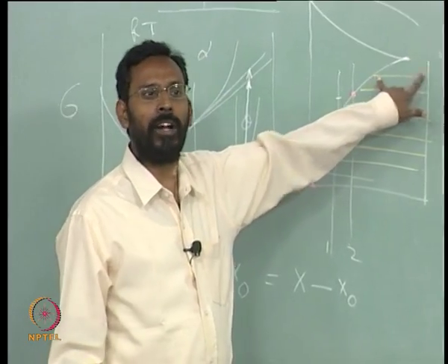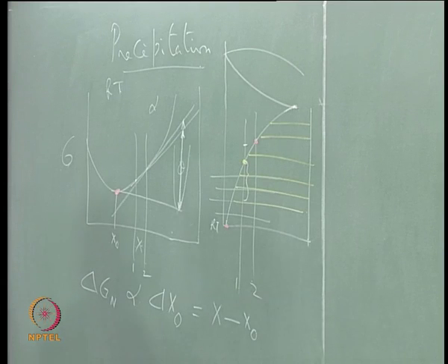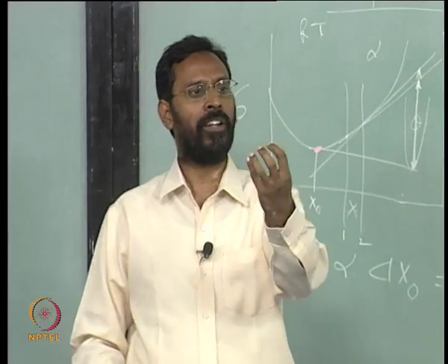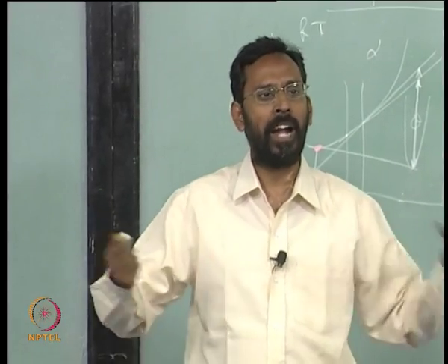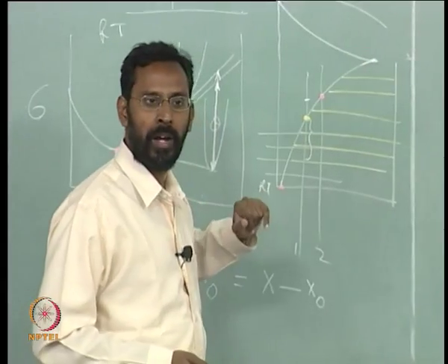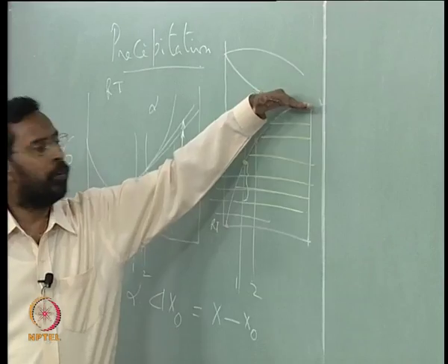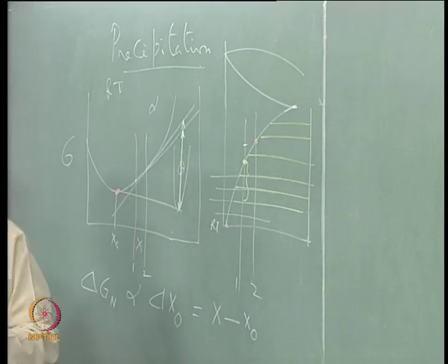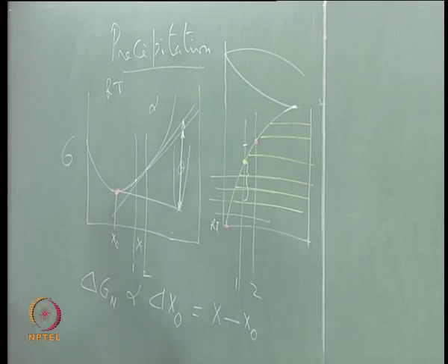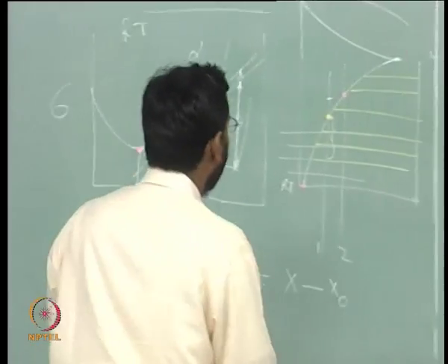and where should that amount of theta go? It gets dissolved into the matrix in such a way that the matrix composition gets richer in copper, because the theta, which is a copper rich phase, is dissolving into the matrix, which becomes enriched in copper content, and that is what you keep seeing. Until the eutectic temperature, you would see that this will keep on happening, and even at the moment you reach the eutectic temperature, you will still have some theta and some alpha